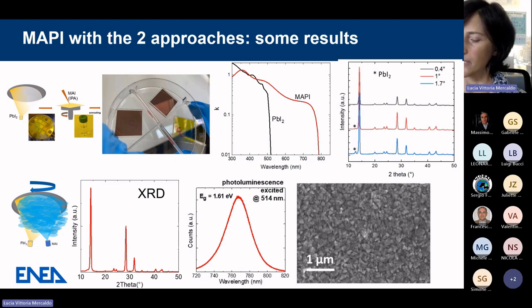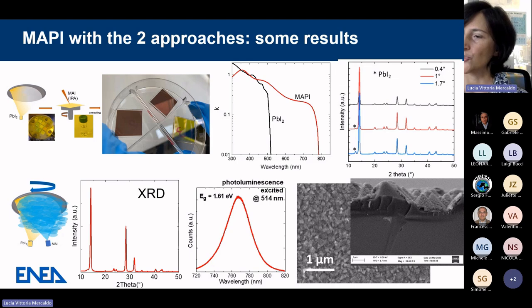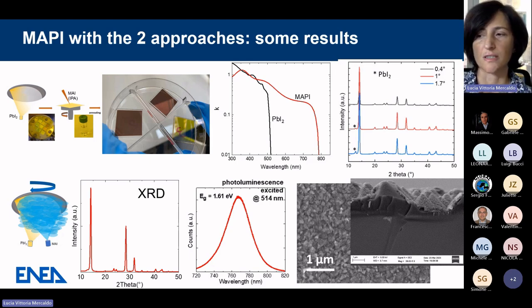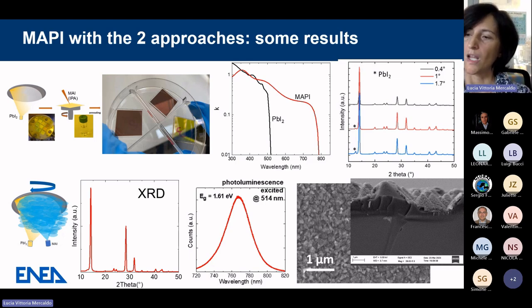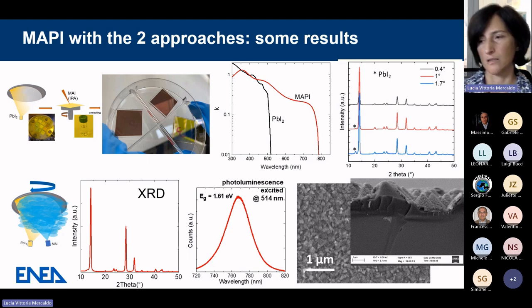And I'm also showing this other SEM micrograph of a deposition on textured substrates. This is the typical morphology of textured crystalline silicon used in photovoltaics, with pyramids in the micrometer range. And you can see the coverage is conformal when we deposit the perovskite film by co-evaporation.